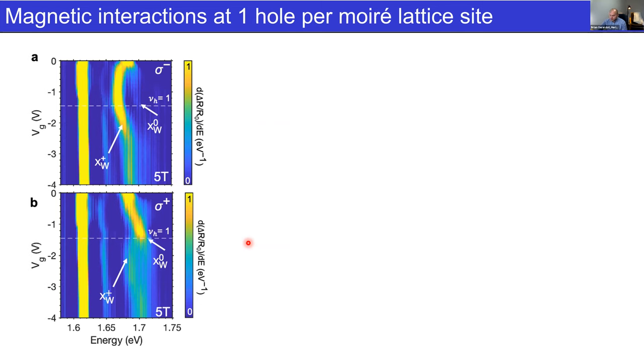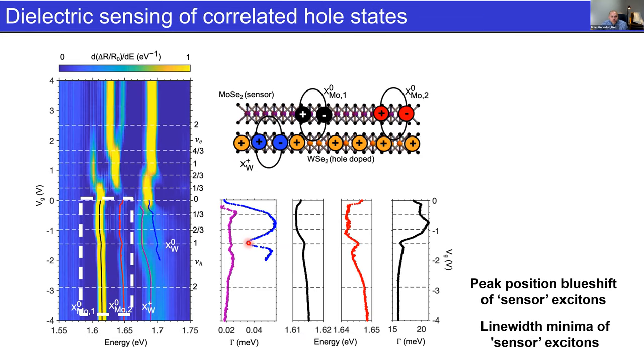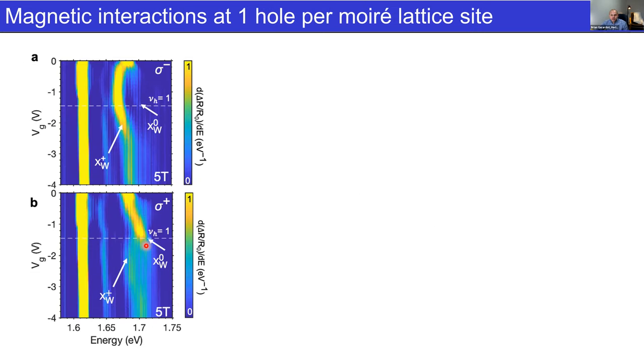So we wanted to look more closely at these two peaks here, the two peaks in this tungsten diselenide that correspond to the A exciton of tungsten diselenide. And what we find is, first we zoom in on these two peaks and we apply a magnetic field, 5 tesla in each case. And we look at the sigma minus and sigma plus polarized light.